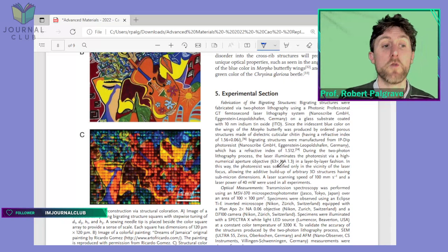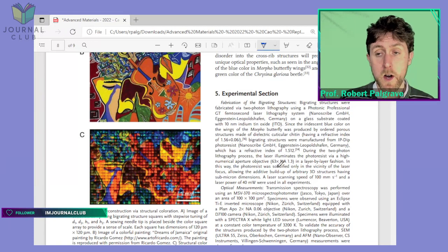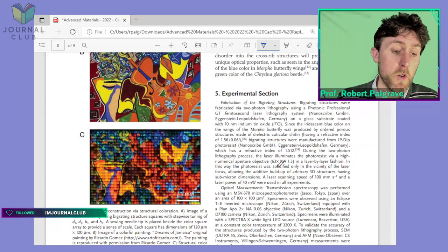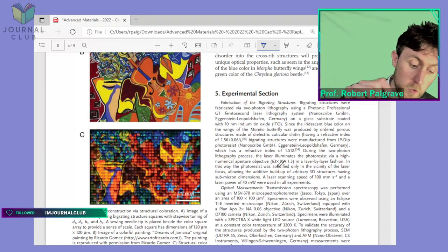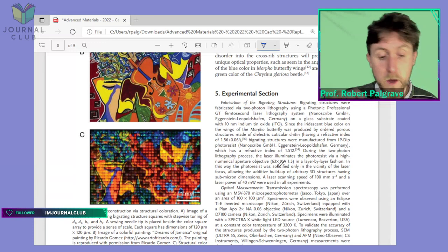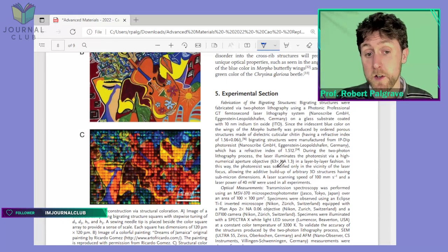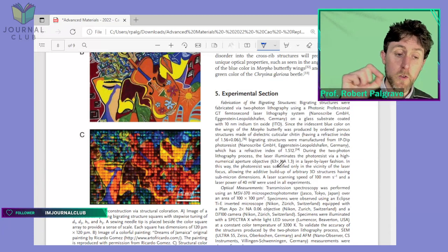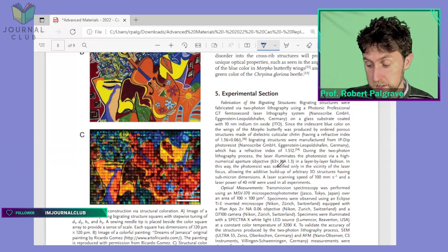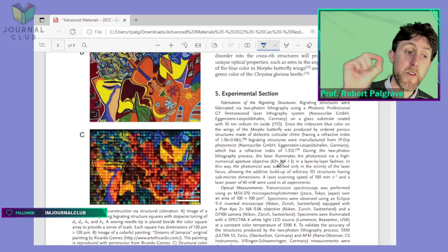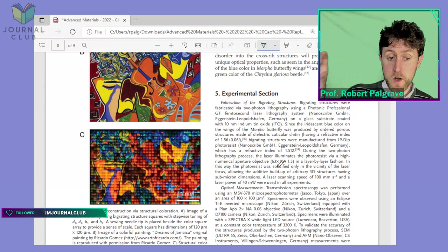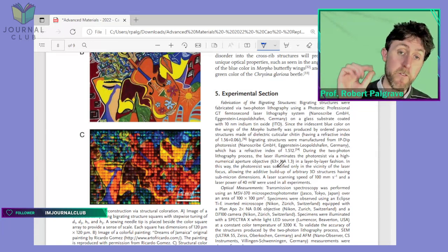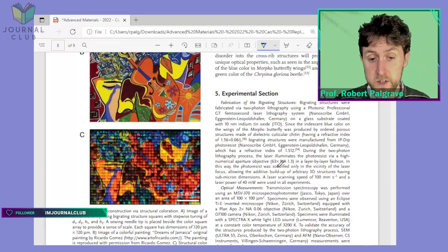Okay, so it's not linear, it's called a non-linear optical material. The solidification works by the square of the intensity. So only at the focal point will the material become solidified, and they can control the focal point of these lasers very, very precisely using their equipment. So they can be very, very precise with the spatial arrangement of the material that they're making. They can make very, very small features on a nanoscale, on a microscale, using this kind of methodology.